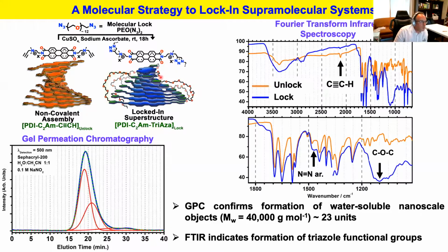And so, of course, we're also using FTIR just to monitor the advancement of the reaction and stop it, essentially. So I won't go into too much detail here, but what I want to mention really is that now that we can use GPC to purify them, we can start asking questions about molecular weight. And so the molecular weight of this type of entity, so that's the Gaussian I'm showing you right there, is around 40,000 grams per mole, and that corresponds to 23 building block units. And that corresponds more or less to the degree of polymerization of 28 that I told you before. So we are able to some extent to capture with a high degree of fidelity, I would argue, the conformation of this supramolecular polymer.